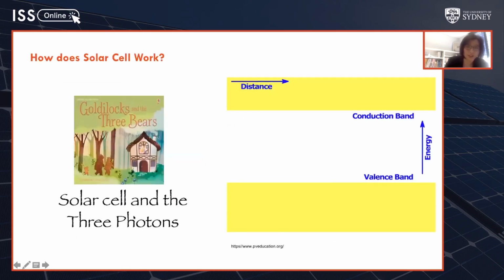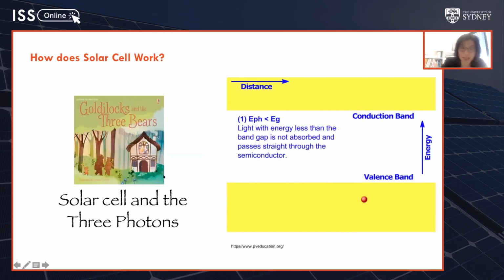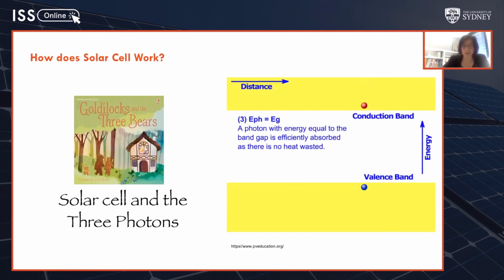So how does the solar cell work? Well, I always like to use an analogy. Instead of Goldilocks and the three bears, I like to say solar cell and the three photons. What happens when you have a photon that has energy lower than the band gap? The photon passes straight through and does nothing. However, when the photon has energy higher than the band gap, the photon gets absorbed, and the energy is used to excite an electron from the valence band to the conduction band. But in fact, the energy is way higher than what is needed, and therefore produces thermalization losses. So like Goldilocks, it's always good to have photons with energy very close to the band gap of the semiconductor, so that the energy is used efficiently to excite an electron without any wastage.